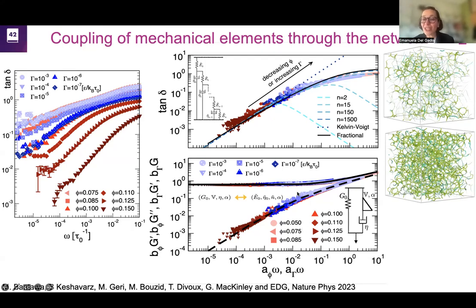But the rheology, in fact, allows us to see clearly that there is a backbone structure that in fact is fractal, and it's embedded in the structure of the gel that develops as the gel gains rigidity, and it controls the rheological response.